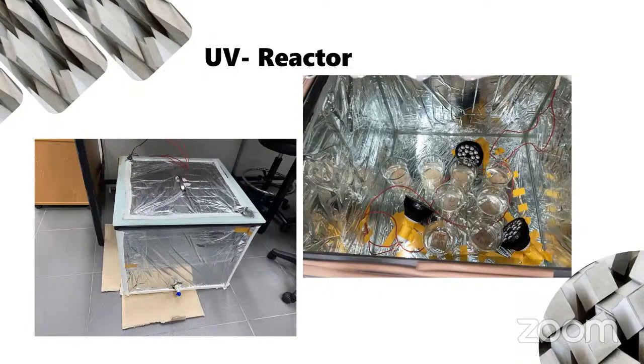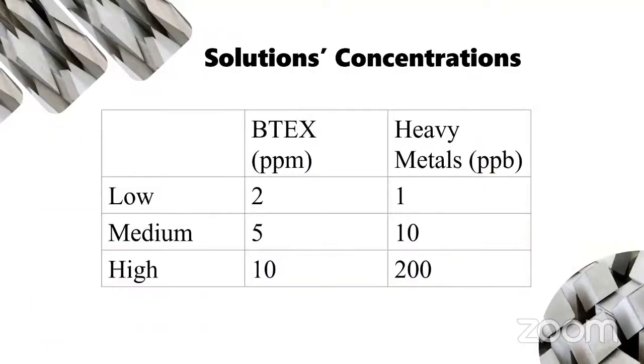At the University of Balamand, there is a reactor equipped with UV lamps, where we can put the beakers, completely sealed, to proceed with the experiment. After we prepared our concrete blocks, we have to prepare the solutions of pollutants. So we prepared 6 different mixes, 3 with BTX at low, medium, and high concentrations, and 3 with heavy metals, also at low, medium, and high concentrations.